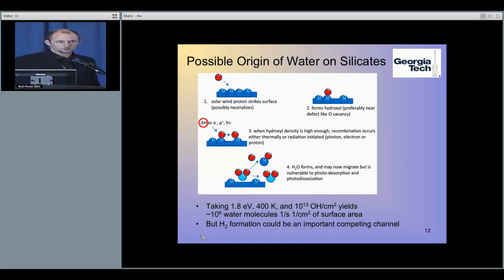You may have seen this graph before. We've shown it a couple times, but it's a mechanism that our group is thinking about for water formation from the solar wind. Basically, hydrogens from the solar wind come in and form hydroxyl groups on the surface. When the concentration builds up high enough, remember I said second order processes: as the coverage builds up, the activation energy, or the temperature at which it happens, moves to lower temperature. So if you build up enough coverage, you can start having the recombinative desorption of the hydroxyls as water.